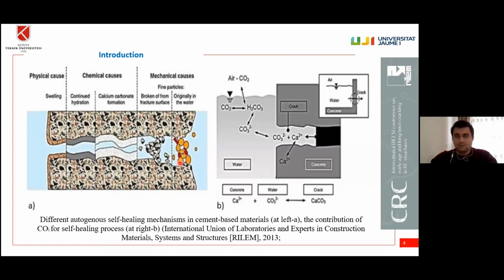First, we can understand the mechanism of autogenous self-healing. There are some different aspects as RILEM proposed. First is the physical cause, which is maintained by the swelling of the cracks. Other is the chemical causes, with continued hydration and calcium carbonate formation. And last is the mechanical causes. This comes from impurities or broken particles of the composites or from the water. As we know, humidity and water contact are very favorable for autogenous self-healing. Why? Because in water, carbon dioxide and carbonic acid, which is a very weak acid, dissociate into carbonates, and these carbonates react with the calcium leaching from the matrix, and then calcium carbonate precipitates, and the formation is done by the ongoing curing.